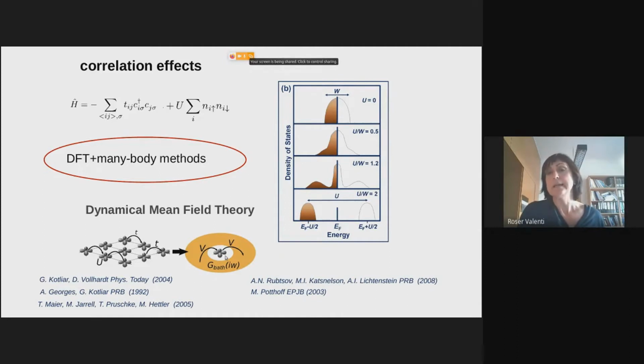So basically by describing your system of interacting d electrons, in the picture I'm showing here, as one central d electron interacting with a bath. But this interaction contains all the dynamics of the interaction. So that means that this kind of approximation includes all local correlations exactly. So this is, in fact, what we are doing when we're describing these correlated systems: combining DFT with many-body methods that take into account these correlation effects.